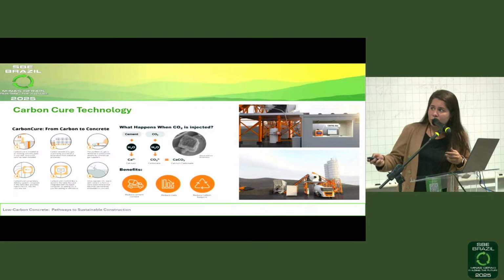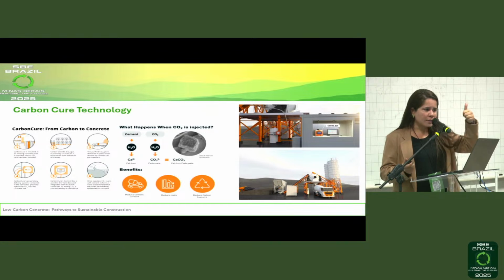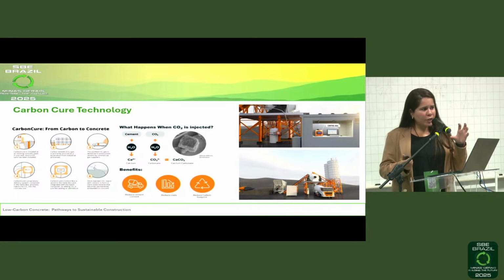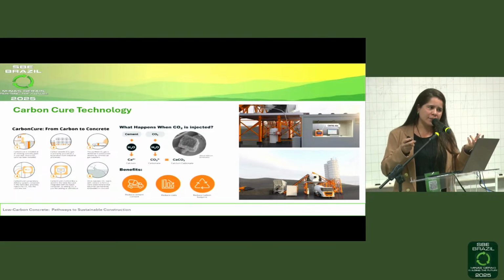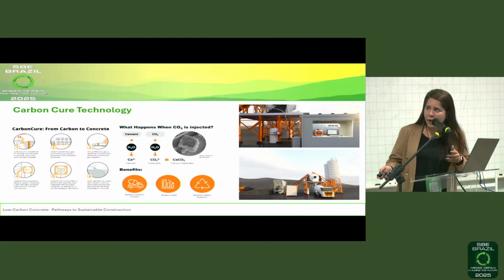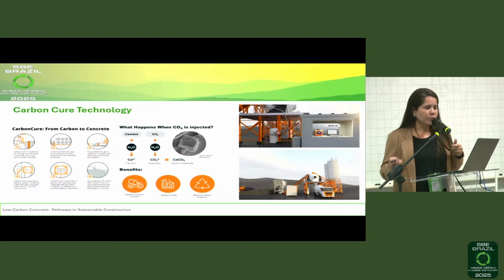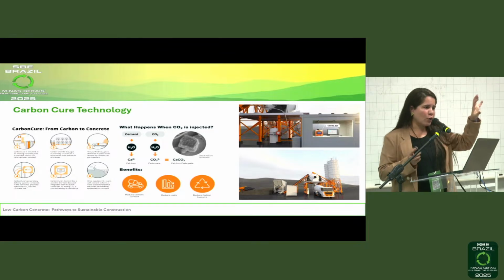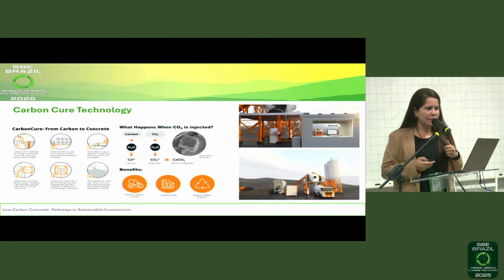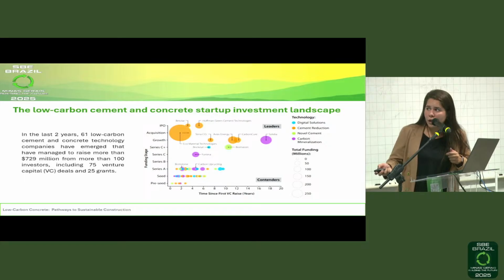When we have the hydration reactions in cement, we have the incorporation of this material as calcium carbonate in the cement matrix, which will make this matrix denser. It increases strength and durability and reduces the amount of cement. So we use less cement and have the same durability, bringing benefits in the reduction of CO2 in the concrete. So this is a project that we will start as a pilot this year using CO2. But in this case, we will buy CO2 and incorporate it into concrete. We won't do the whole process. We won't do the capture, purification, processing, and distribution. We will buy first, and then we will start this work reducing the load of cement in the operations of concrete.